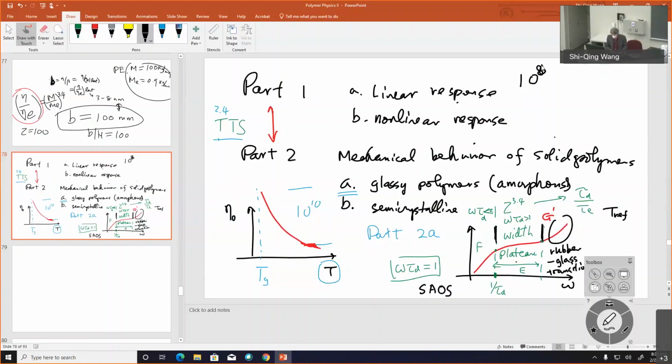What we know is your familiar parallel plate, where you can move one of your plates torsionally back and forth, back and forth. Because of many issues, including compliance issues and inertia issues, it cannot oscillate very fast. So the upper limit in all commercial instruments is 100.